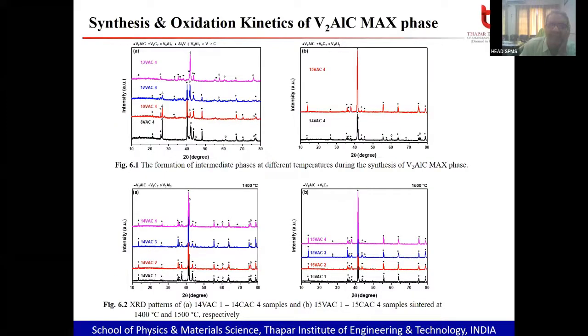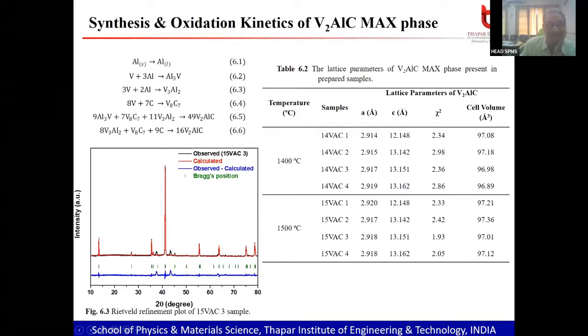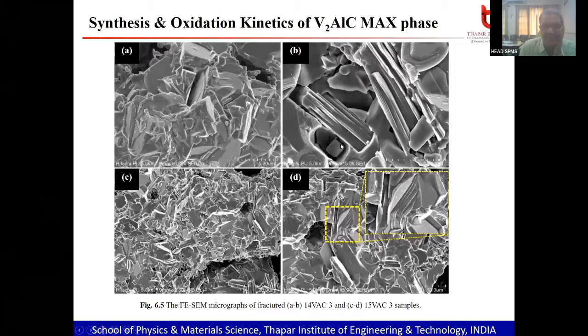This is another category of MAX phase, the third category, V2AlC. This is also the 211 category of MAX phase, where you will find that similar structural features exist. And let me tell you that you will never get a pure MAX phase. If you look at the XRD features I have shown over here, there is a very slight amount of carbides which are also present. So in the structural feature also, if you see the B micrograph here, this is the faceted structure of the carbide, whereas this is the layered structure of the MAX phases here. And here you can see that this bendability indicates that the material is flexible in nature. Okay.